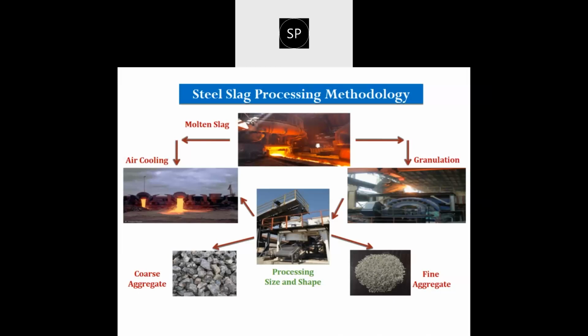In comparison to the steel slag, the blast furnace slag has low density, and therefore conversion of this sort of material in the form of sand sized particles is pretty easy in comparison to the steel slag. Besides that, the steel slag contains a high amount of manganese and different sorts of heavy metals, which may cause environmental issues. Therefore, the conversion of steel slag in the form of sand particles has not been attempted so far. And besides that, it is a bit of a cost consuming process in comparison to conversion of blast furnace slag in the form of granulated sand particles, or these sand particles can be further ground to get converted in the form of ground granulated slag cement.